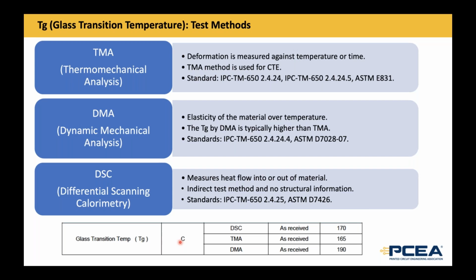Okay, and the second method is the DMA, the dynamic mechanical analysis, which measures the elasticity of the material over temperature. And as I mentioned earlier, due to the nature of the test methods, how they're measured, the values are different. Typically, the TG by DMA is higher than TMA. You can see in the example property here, the TMA value is 165 degrees, whereas the DMA is 190.